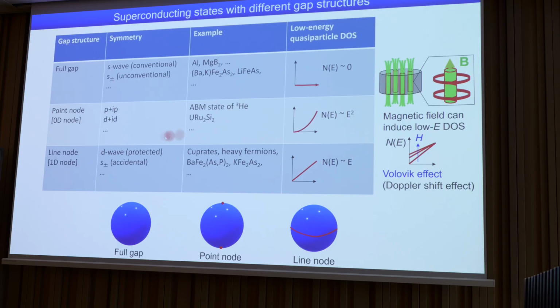For example, if you have a line node state, you would expect E-linear effects at low energies. But if you apply a magnetic field, you immediately create low energy states, which is called the Volovik effect. This has been very well known, and this observation can be used as evidence for line nodes.